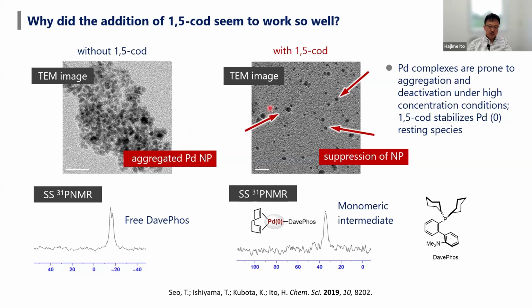This is a TEM image in the presence of 1,5-COD, where palladium nanoparticle formation can be suppressed, and less palladium black was found in the reaction results. Solid state NMR also shows that palladium(0) species coordinated by phosphine ligand and 1,5-COD are present in the reaction mixture. This clearly shows that addition of 1,5-COD stabilizes the palladium(0) resting species in the cross-coupling reaction, because palladium(0) species can aggregate due to high reaction concentrations in the ball milling conditions. Without 1,5-COD, palladium(0) decomposes to palladium black more easily.